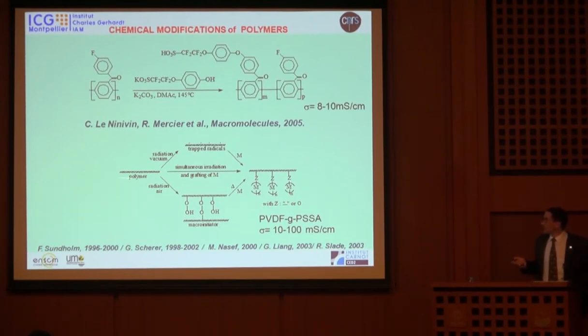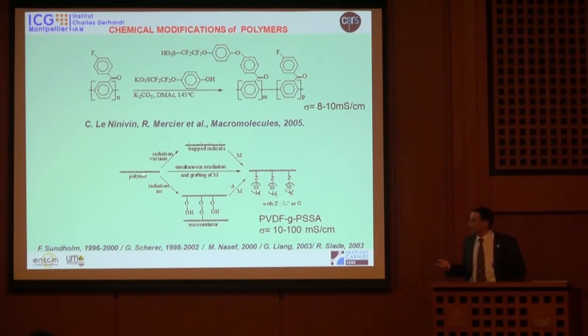So the conductivity was not so high, but the target was for direct methanol fuel cell, in which they had successful results. Another strategy which is very well developed in the world by Sundholm in Finland or Scherer in Switzerland, Nasef in Malaysia, Liang in China, Slade in UK, or even in Japan, I know a lot of groups are working, is to take a fluorinated polymer and to make some irradiation. So you can do irradiation by ozone, by electron beam, by gamma ray also, and indeed it's not very well specified if you have trapped radicals, if you make a simultaneous irradiation in grafting, adding a monomer, or if you make hydroperoxide or peroxide. But this kind of systems are very efficient because these macroradicals enable to initiate the polymerization of a monomer, or this peroxide or hydroperoxide also can initiate the polymerization.